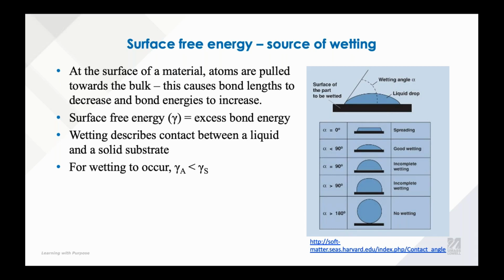The underlying phenomenon that dictates wettability is related to what's happening at the bulk versus what's happening at the surface. So on the surface of the material, the atoms are being pulled towards the bulk. This is our classical understanding of this phenomenon, which leads to this excess bond energy on the surface that we describe as our surface free energy. And so wetting in this case is describing the contact between them, and for wetting to occur, the surface free energy of the liquid, of the thing that's spreading on the surface, needs to be less than that of the substrate. If we go to the next slide.